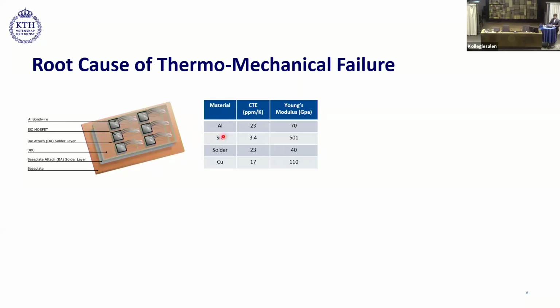If you look into this picture, we see that the coefficient of thermal expansion of these materials is different. For example, silicon carbide is 3.4 and aluminum is 23. So this introduces a coefficient of thermal expansion mismatch. And also the Young's modulus is different. In general, I would like to say that the thermal and the mechanical properties of these devices are different.